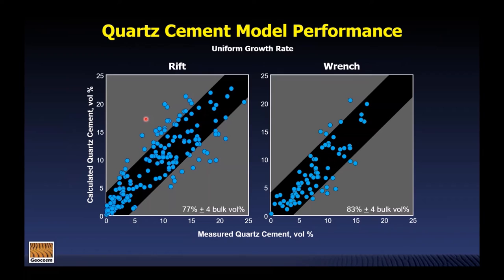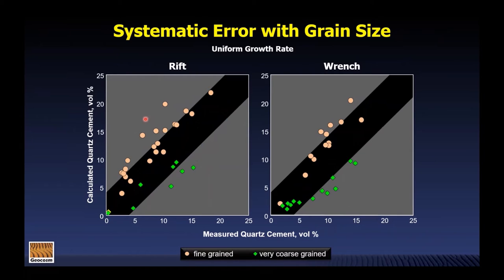And so she went through these data sets and many other data sets in great detail. And she indeed discovered that there was a very systematic error that she observed in virtually every data set that she looked at. And to reveal that error, what I'm going to do now is strip away all the points in these plots with the exception of the grain size extremes. And so here, what you can see in both of these data sets is that we tend to overpredict, we're predicting too much quartz cement in the fine grain rocks, while predicting too little quartz cement in the very coarse grain rocks.